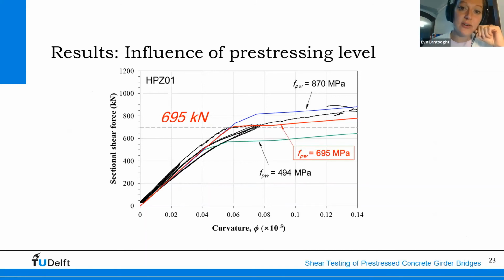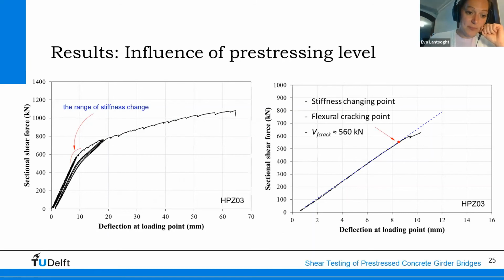One thing that we studied further is the influence of the pre-stressing level. So as I mentioned, we looked at a detailed sectional analysis to find or fine-tune the value of the pre-stressing level in the tendons based on the stiffness and the moment of cracking here. That was not just based on the sectional shear force versus deflection graphs, but also really zooming in and seeing where the stiffness changes and what we can analyze from a sectional analysis there.